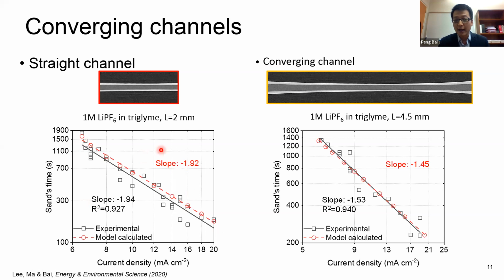meaning that the exponent here, minus 1.92, is very close to the theoretical prediction of minus 2. That means there is no geometric effect, because the theory didn't consider any geometric effect, and you match that. But when you have this converging channel, it deviates from the theoretical prediction.